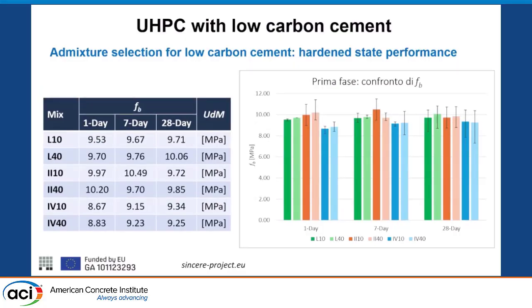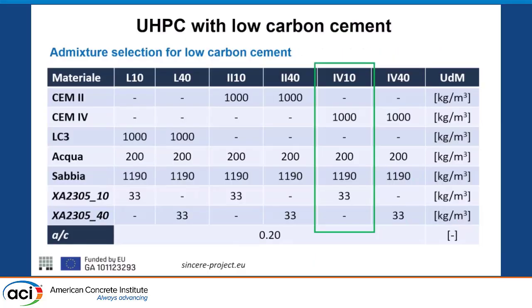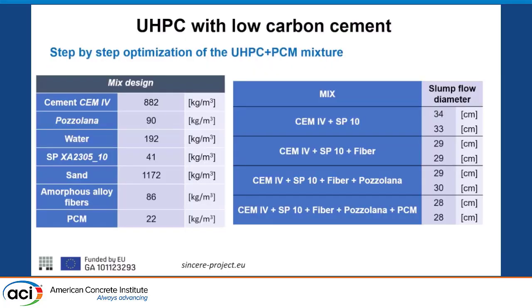But also what was important, because we use these materials not only for compressive strength, we use them for flexural toughness as well. So with the fibers, we were able to obtain a maximum flexural modulus of rupture, let's say, of about 10 megapascals. So it was a good result as well. So we then selected the CEM IV, the pozzolanic cement, as a composition, and we wanted to further dope it, mixing in some natural pozzolana, just to further reduce the clinker content.